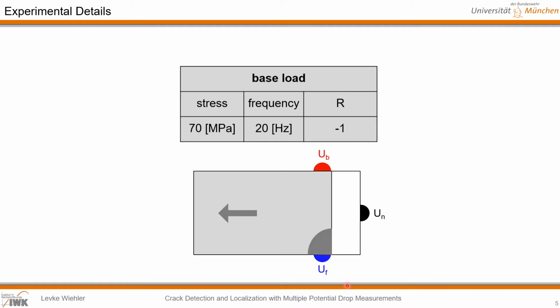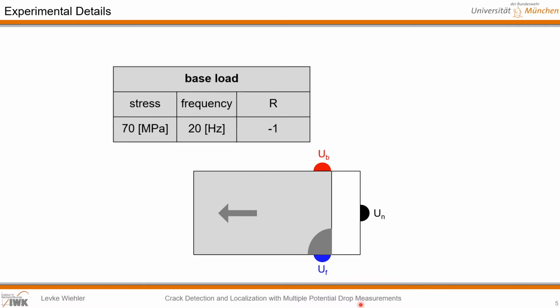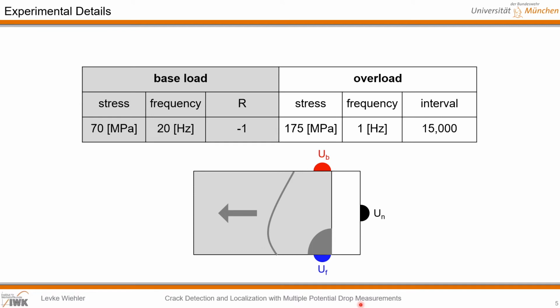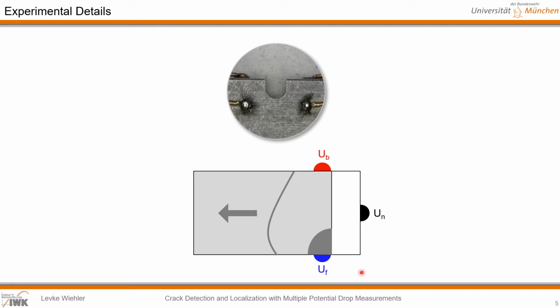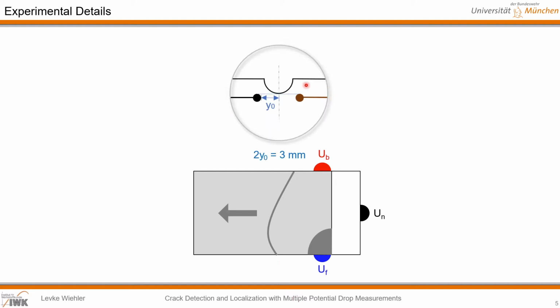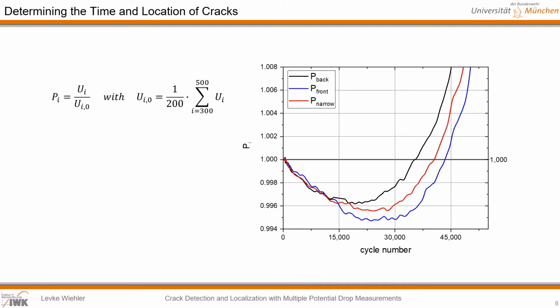To enable a direct comparison between the potential drop measurement and the real crack geometry, the crack front was marked on the fracture surface by introducing overloads at defined intervals. For the potential drop measurement, copper wires with a diameter of 0.2 mm were laser welded to the specimen. The distance between the two contact points of a potential probe was 3 mm. The measured potential is significantly influenced by the position of the potential grips. I will now follow up with the determination of the time and location of cracks.